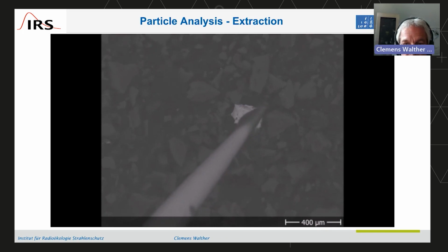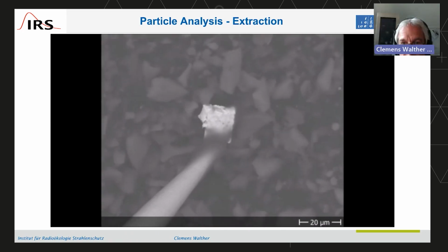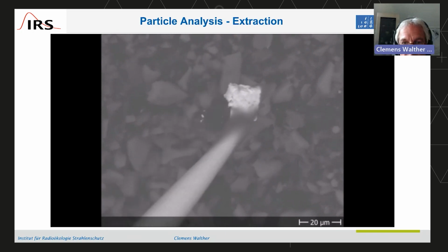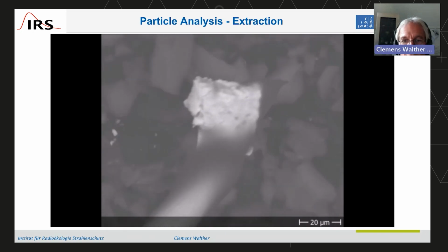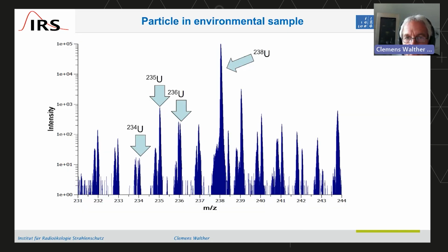The particle is on the substrate right now, and as soon as you are in a good position, you touch that particle, then you apply an electron beam to harden the glue, and when that was successful, you can single out that particle and have it mounted on your tungsten tip for further investigations.